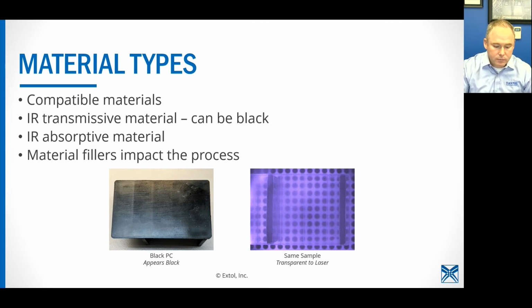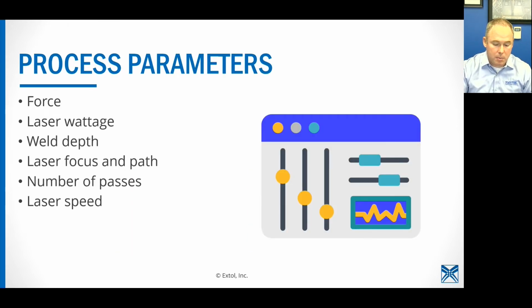So filler materials, we talked about that some. It can impact the process. Just need to be mindful of that. With respect to process parameters, we'll just touch on this quickly. Force, laser wattage, weld depth, the focal point of the laser in the path. Obviously, you need to hit the part, and number of passes and laser speed. Those are the levers we're pulling when we dial in an application.